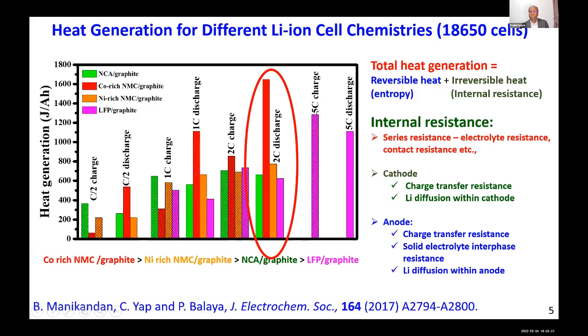And there is another advantage with LFP chemistry, that is the PO4 bonding, which Dr. Kaswara also mentioned. PO4 bonding is extremely strong. By chance if your BMS fails, and you go beyond the cutoff voltage of 4.3 volt for the charging cutoff voltage, then the oxygen is not released. Whereas in all these oxide materials, oxygen is released by chance if you exceed this cutoff voltage, which is about 4.3 volt. Now the question is, why so much heat generation?